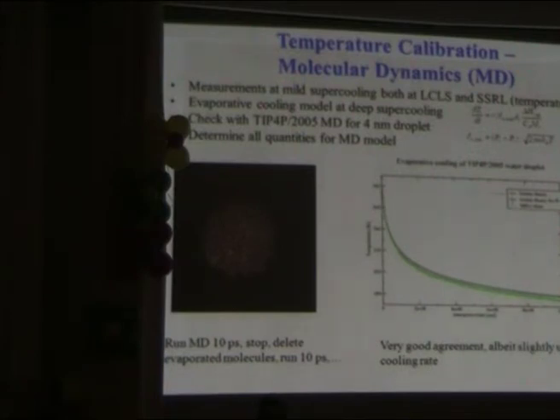Every once in a while, water molecules evaporate from the droplet. In the simulation, we can measure the temperature, and that's the green curve here. Now, to apply the Knudsen evaporative model, we only need thermodynamic quantities. These we can define from the simulation for this particular model. And when we mathematically model, using these quantities in the model, we have a very good fit.